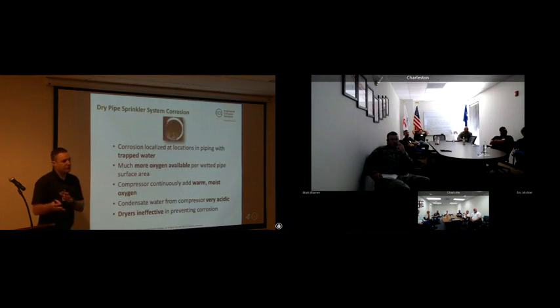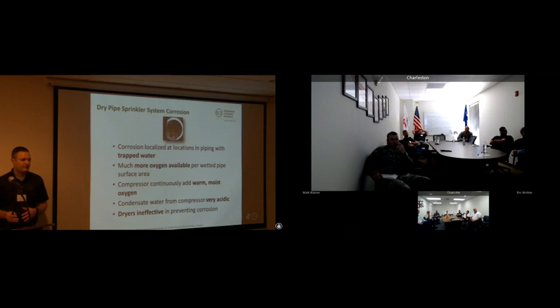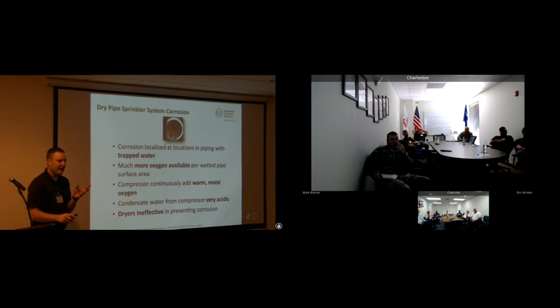So let's switch from talking about wet systems to dry systems. We have the same mechanics that are happening inside the system, but they're happening in a little different ratios. We have less water, we have more oxygen. And in this case, in a dry reaction system, we might have a galvanized pipe. So in a dry system, instead of looking for the high points where we're trapping air, we're looking for the low points where we're going to trap water.